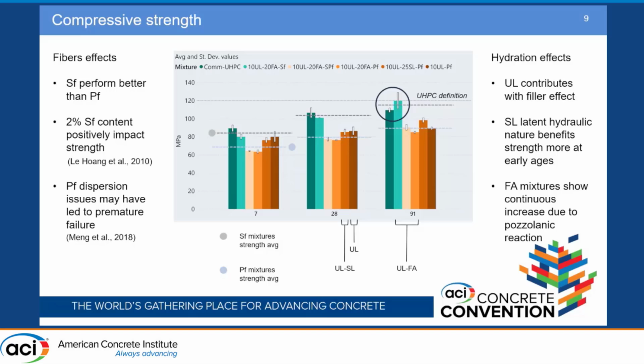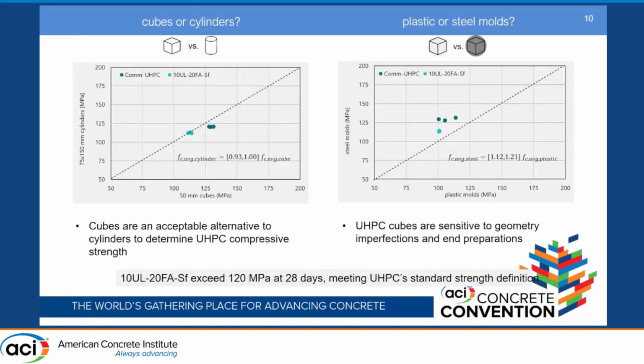You might have noticed that these strengths are not particularly high for UHPC. That was the reason why we defined ours as a ultra high performance concrete, because as we said, we expected results not that high because of the high replacement level of SCMs and PLC that we use. And also because we didn't use any kind of high temperature curing condition, but just normal curing condition.